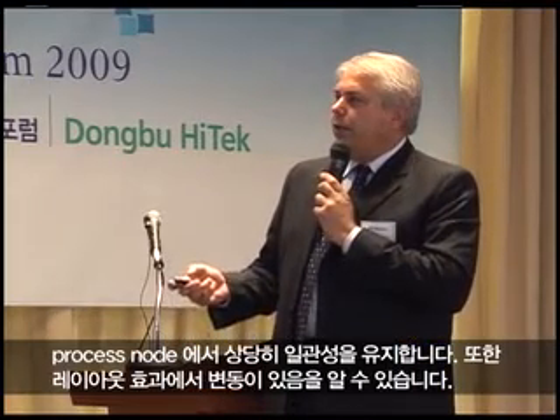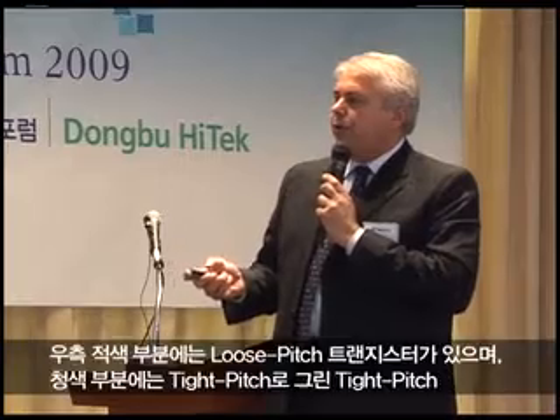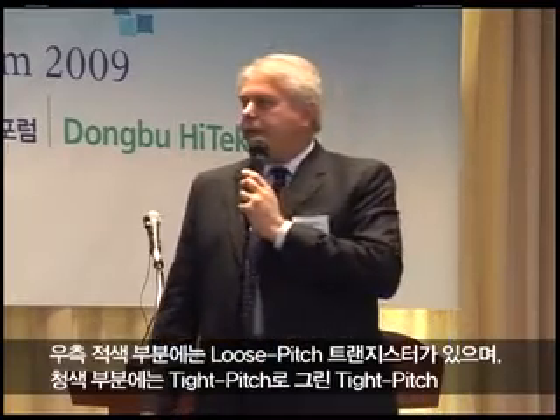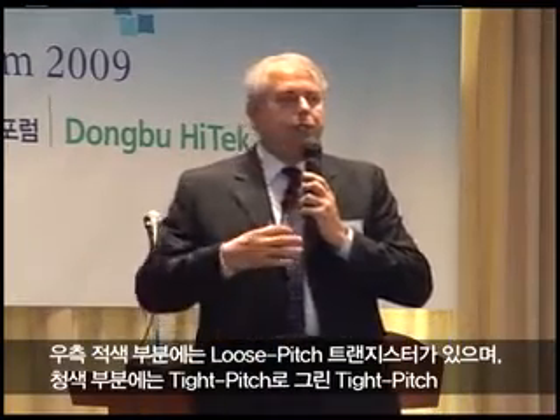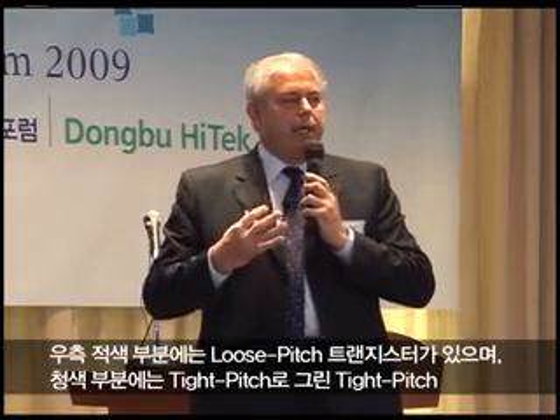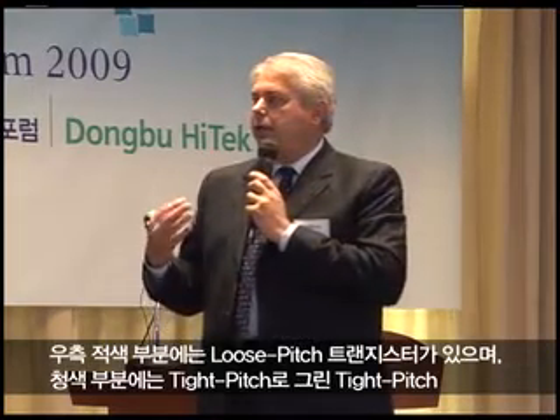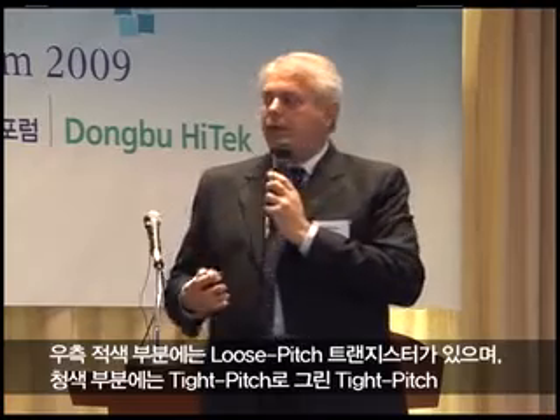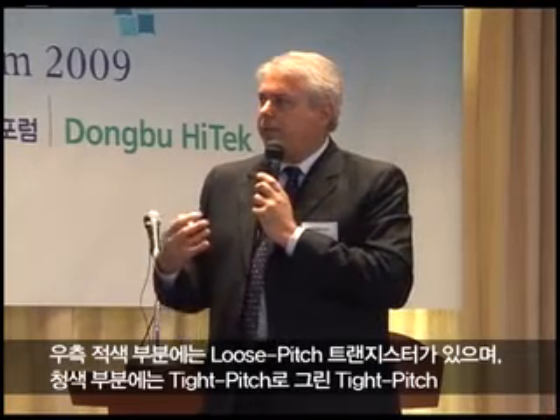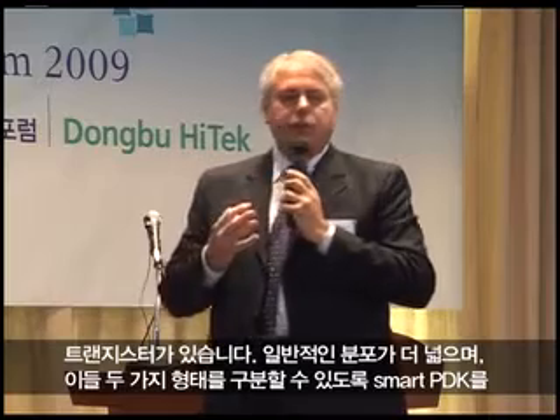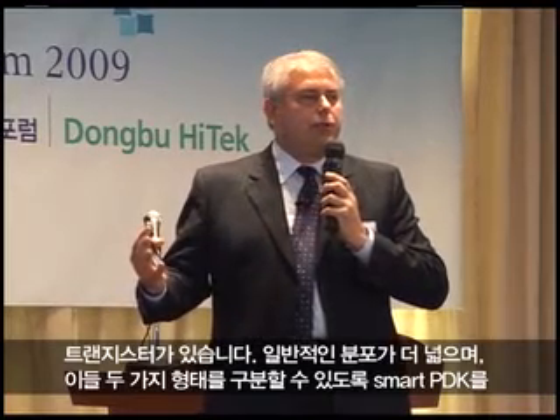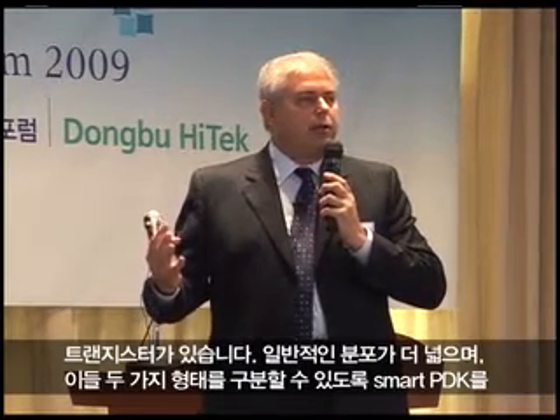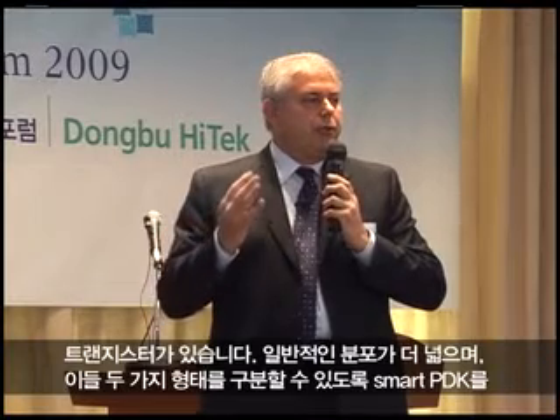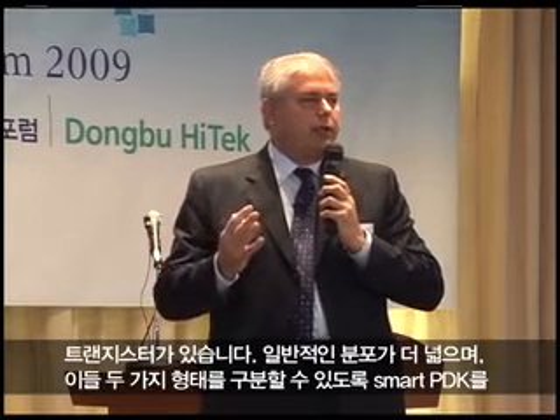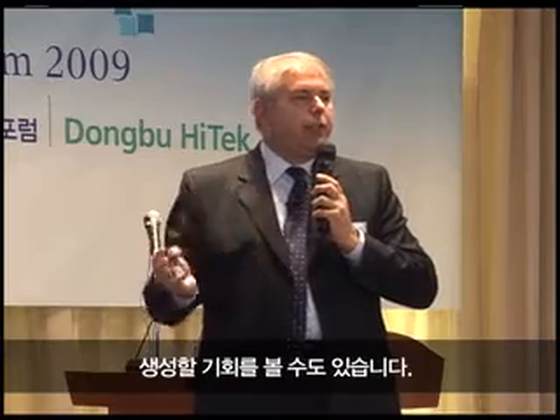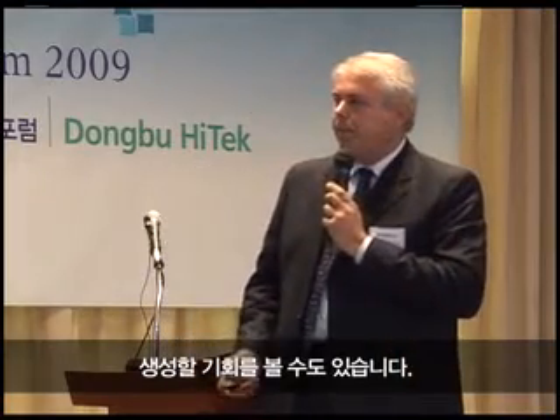And you can see the variation also from the layout effects. On the right side, in the red, you have the loose pitch transistors. And in the blue, you can see the tight pitch, same transistors that are drawn with a tight pitch, and you can see that just the general distribution is wider, or you can see an opportunity to create, let's say, a smart PDK that can differentiate between these two types.